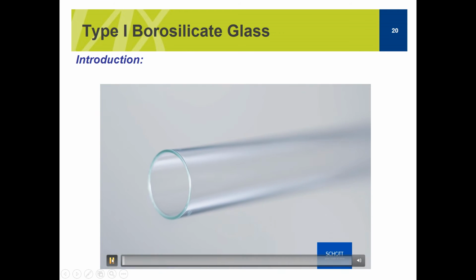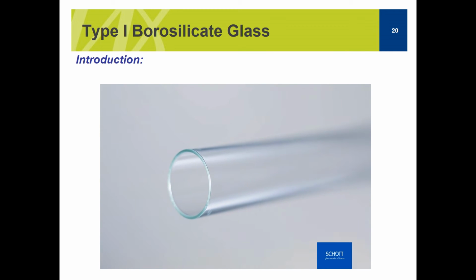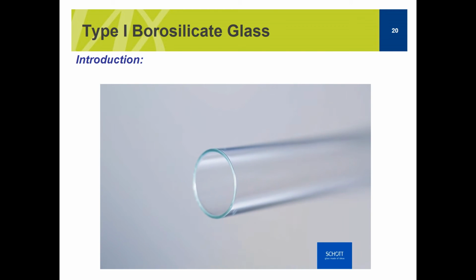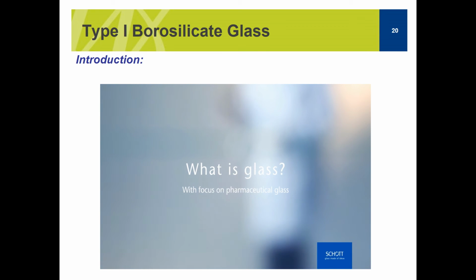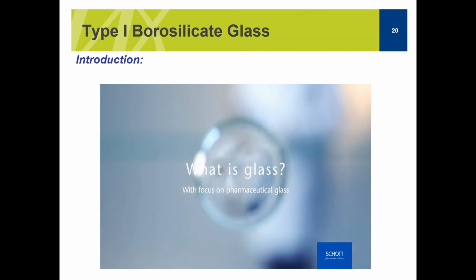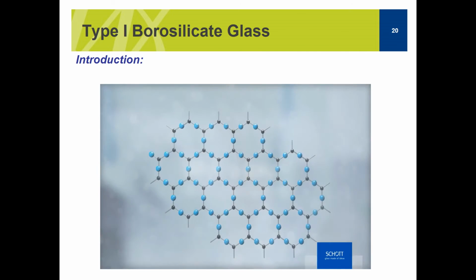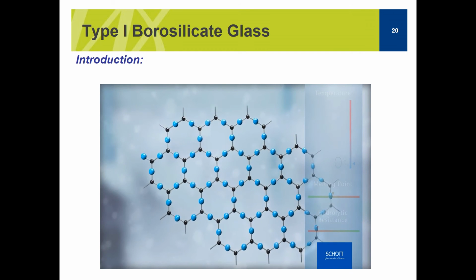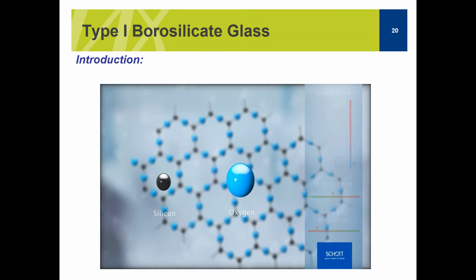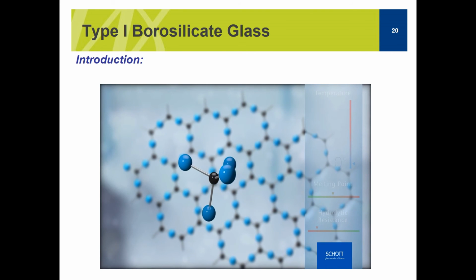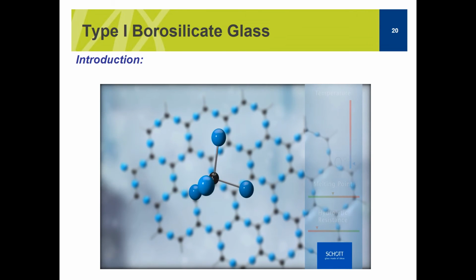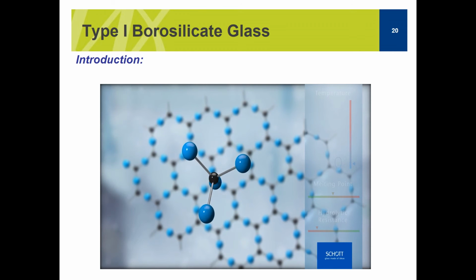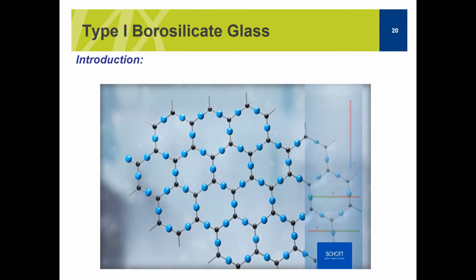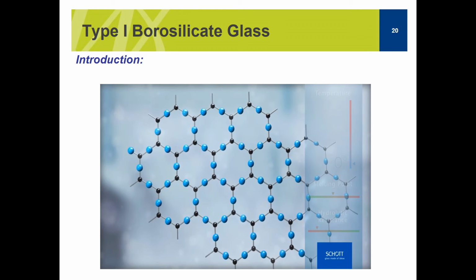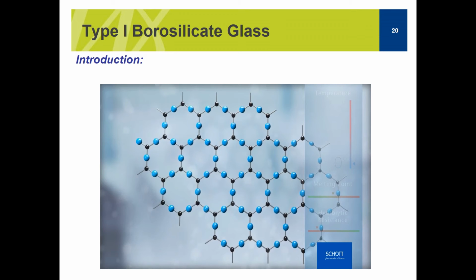Glass plays a role in many aspects of our lives. One particularly important area is the pharmaceutical area. Here, glass needs to satisfy high standards. The quality that we have today largely results from scientific and practical experience. But where does this glass come from? Glass starts out its life as sand, which in its purest form is called quartz, a mix of silicon and oxygen. Surrounded by 4 oxygen atoms, this silicon forms a tetrahedron. To simplify this, the structure will be shown in a 2-dimensional way. The overall structure demonstrates perfect symmetry, as in a crystal. Glass, as we know it, has an amorphous structure.